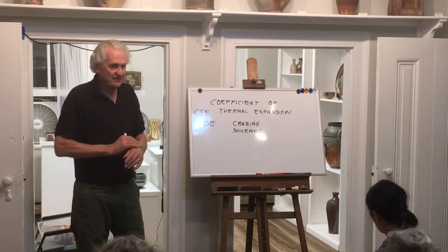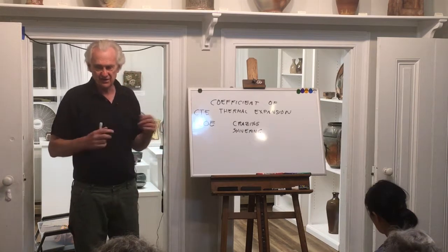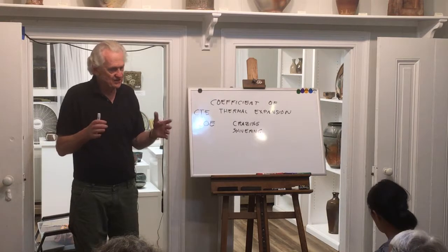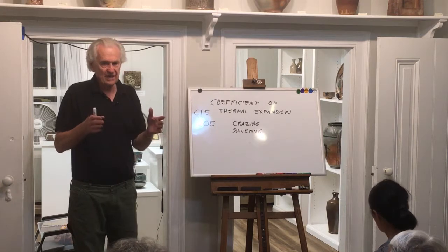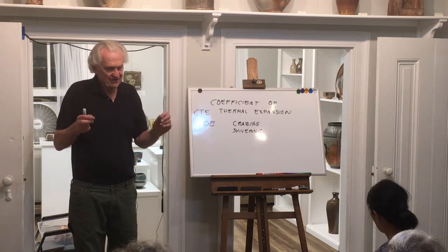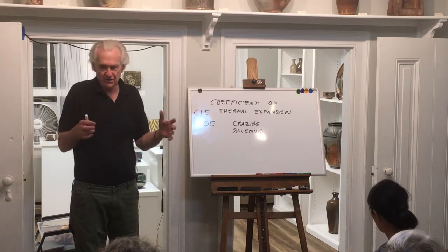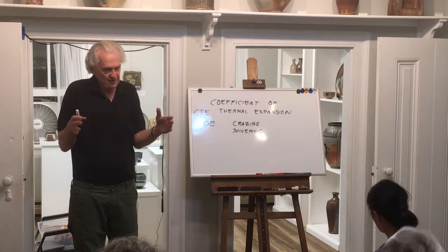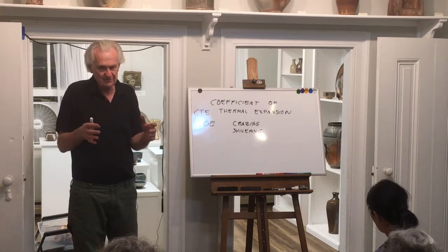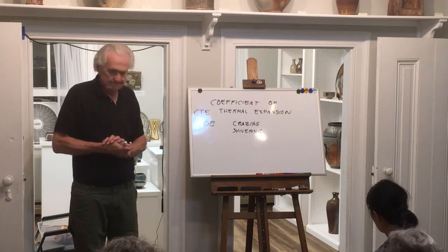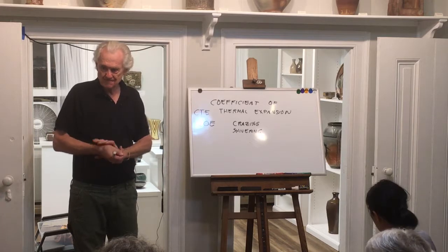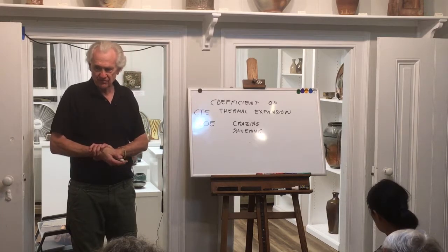So that's the ideal, and this is what they do in industry and in ceramic companies where they can engineer these things more precisely. They'll formulate a glaze to contract slightly less than the clay, so the clay is squeezing it, and that's the strongest possible situation for the glaze, to be squeezed slightly by the clay. So if you are having issues, it's just a matter of changing materials to find the right fit.